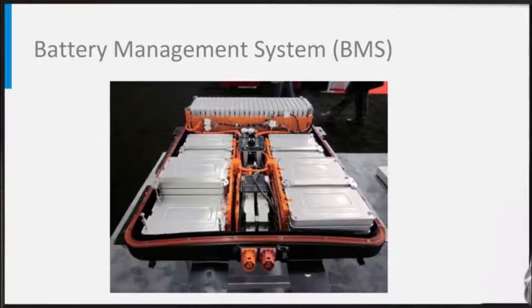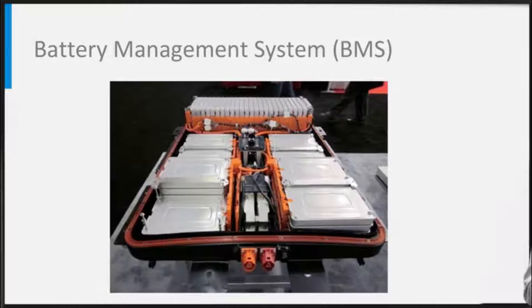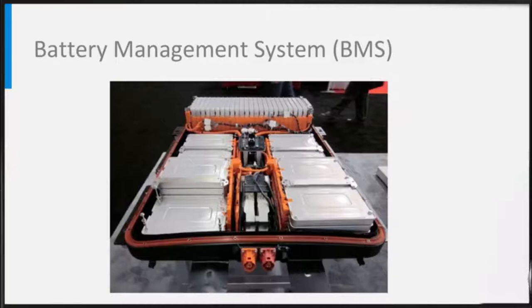The BMS continuously monitors the voltage, state of charge, and current over the individual cells in the battery pack, and is able to regulate how individual cells are charged and discharged. One of the most important roles of the BMS is to balance the state of charge of the individual cells, to prevent individual cells from being at a relatively high or low state of charge, which would expose the electrolyte to relatively large overpotentials and lead to electrolyte degradation — one of the major contributions that shortens cycle life. A sophisticated approach is to shuffle energy from the highly charged cells to the least charged cells. In this way the BMS is vital to achieving a long cycle life of the battery pack, in combination with providing optimal performance.